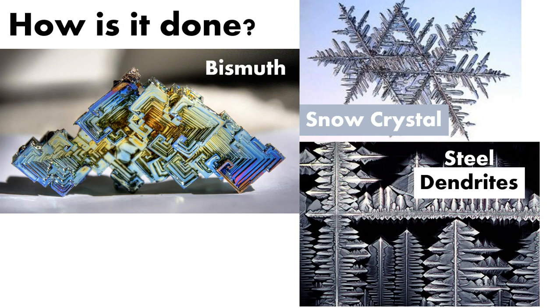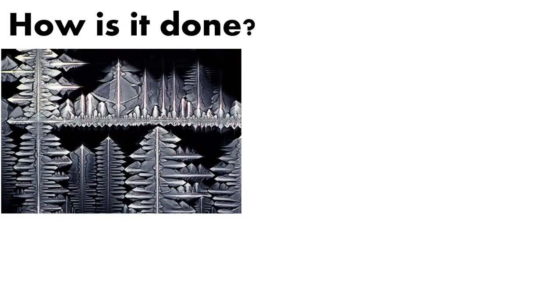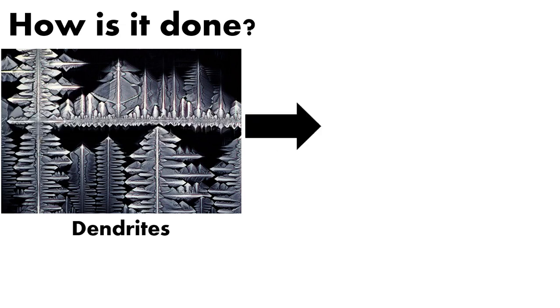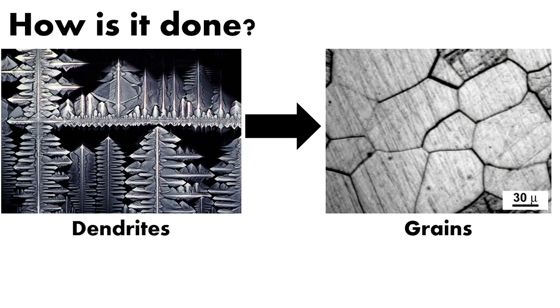So let's look at more of that process. We start off with dendrites in the steel, and as it goes, it starts to grow until you get something that's solidified, and these are grains. These are steel grains that have grown from dendrites and then solidified until what we see here is steel, and you see this at 30 microns right here. So 30 microns, so that's steel.